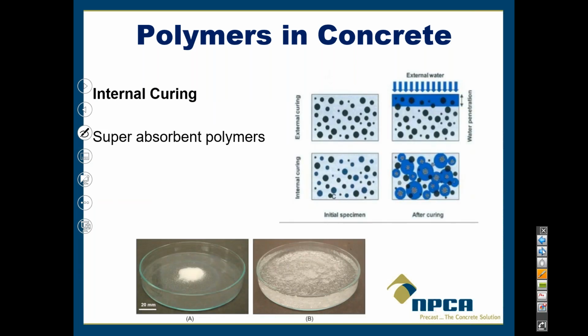Another thing that polymers are used for is internal curing. Now, you might have heard of internal curing through using lightweight aggregates, where the aggregates are soaked with water and then they release water from within the matrix. Because if we do normal curing where we apply moisture or retain moisture to the external of the structure, then really the water penetration is limited to wherever the surface is. And then on the inside, you can have desiccation caused by water leaving the area, whereas internal curing keeps the moisture in the concrete, so you don't have that desiccation.